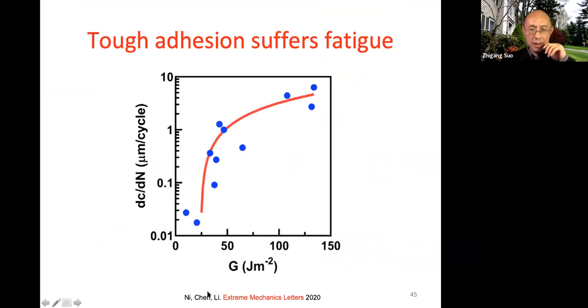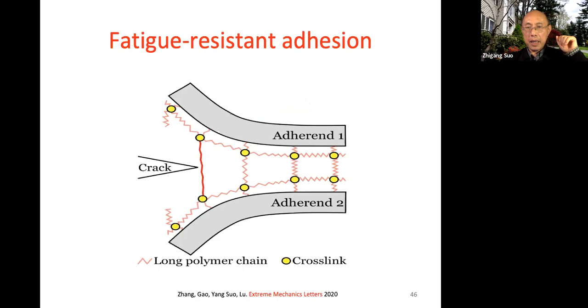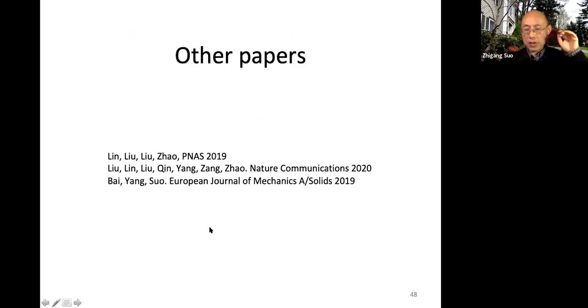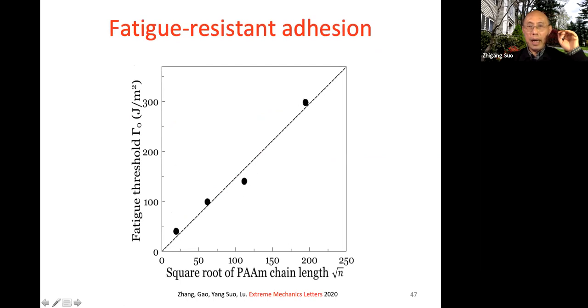Anyway, then this Lee became a professor. He was a student in my group and a shared student with another group, and became a postdoc at Mooney's lab. When he was at Mooney's lab, he created this work, tough adhesion. And then he became a professor. He published a paper. He showed this fatigue threshold is about 10 joules per meter squared. Again, the threshold of adhesion is very low. So then here is our paper. Now we find a mechanism just by elastic dissipator. We can have adhesion energy, fatigue threshold, all the way to multiple hundred joules per meter squared.